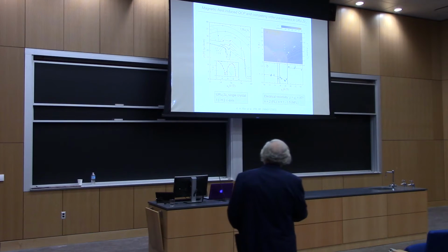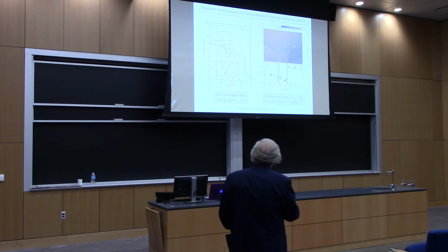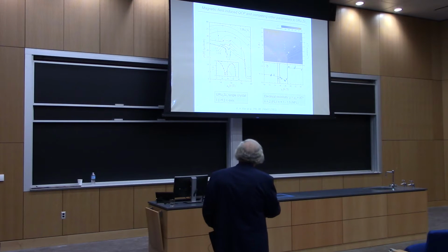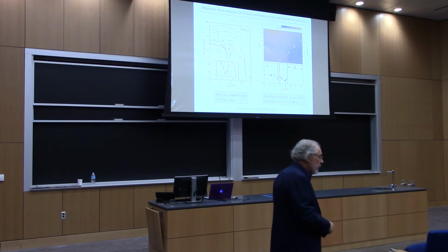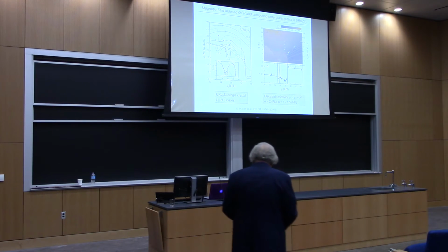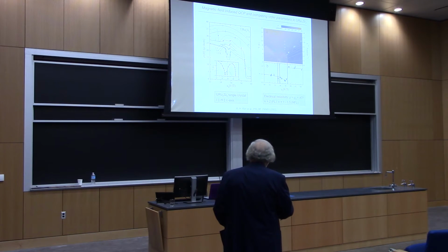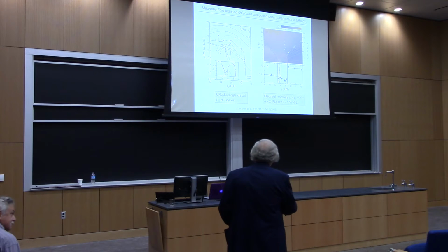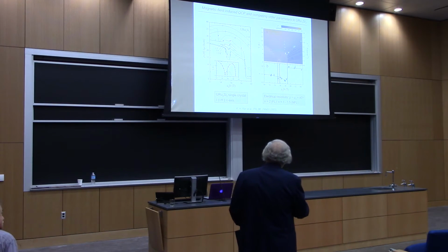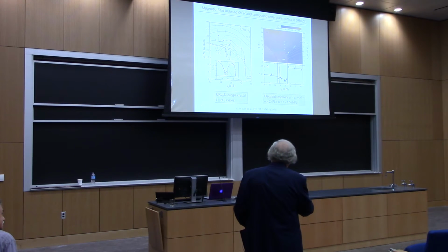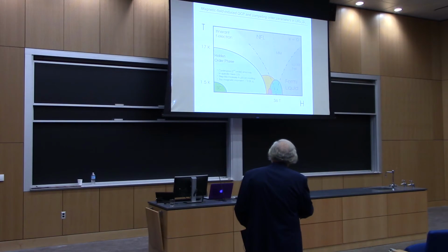And this was motivated by work on pure URu2Si2 done some time ago. But anyway, at very high fields, you see all kinds of features in the resistivity, thermal expansion, magnetization, and so on. And from that work, many people have worked on this, you can deduce a phase diagram. And so you suppress the hidden order phase. This is a metamagnetic transition. And then there's a whole set of other quantum phases that occur near the quantum critical point associated with the hidden order phase. And that just shows it in a little bit more detail schematically.